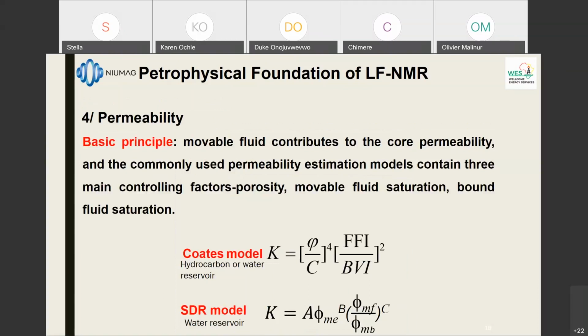The fourth information we are going to have is the permeability. The permeability depends on the movable fluids inside the core, and there are two equations to do this. The first one is the Coates model, which is a very supple and very easy to use equation, depending on the porosity, the free fluid, and the bound fluid. The second is the SDR model, Schlumberger-Doll Research Center model. It's valid only for water reservoirs. However, it works in some cases very nicely for gas reservoirs, but it's more for hydrocarbons. Generally, people prefer to use the Coates model. It's giving a better result. So you remember we have the porosity, the free fluid, and the bound fluids, and we calculate the permeability.